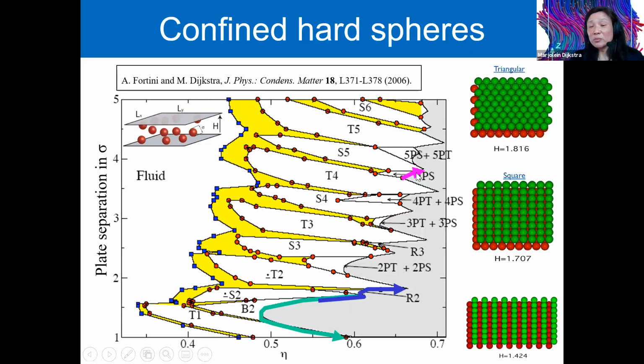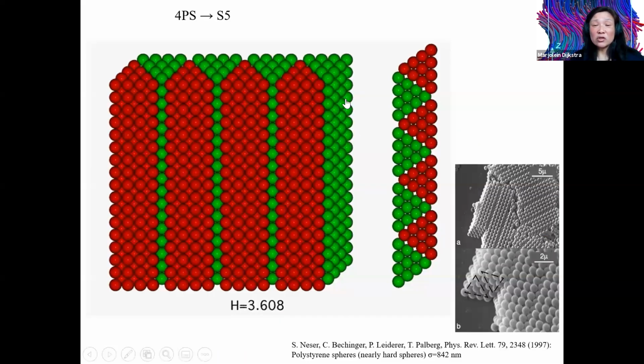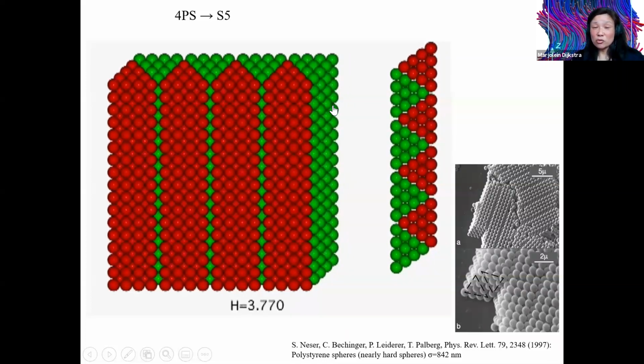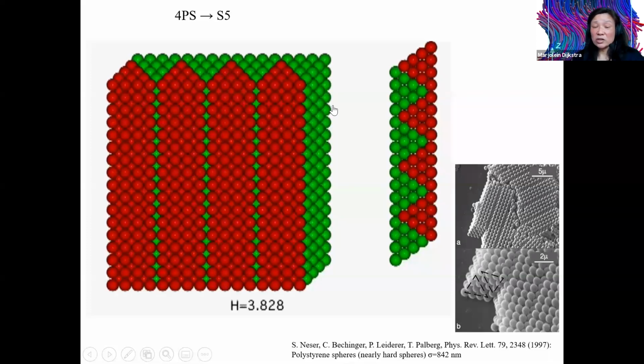So one can also look at these prism phases. There's a whole zoo of these prism phases. They're denoted by a number, which is the number of layers in these prisms. And we can see if you start with these prisms, there are these twinning planes in between the prisms. We can increase the plate separation, and then it goes to 5 square layers. So there's a whole zoo. Also these prism phases have been found in experiments, in the group of Thomas Palberg.